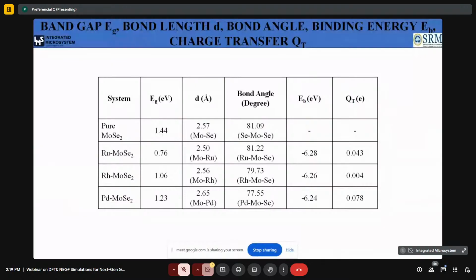Which implies that structural modification has happened, and that is also reflected in the band gap. A reduction in band gap was observed after creating very small structural changes, and that we observed after incorporating the dopant. The stability analysis we have done by calculating the formation energy. It is an exothermic process, and the formation energy values again satisfy the stability, confirming the stability of the system.